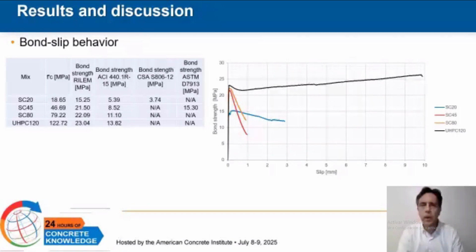The table on the left compares the measured bond strength tau from RILEM testing with estimates derived from the following design standards: ACI 440.1, which is based on pull-out behavior, CSA S806, which provides more conservative guidance, and ASTM D7913, a standardized pull-out test method. A key observation is that all normative methods yield significantly lower bond strength values compared to the RILEM results.